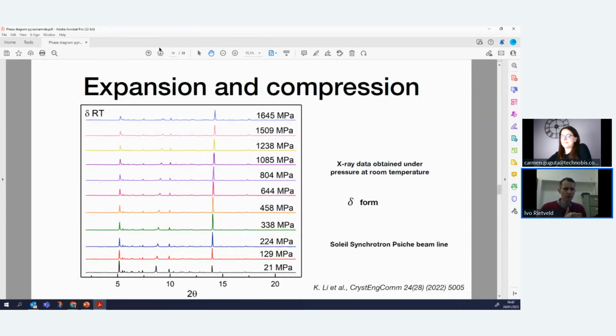Well, after that, obviously, this may not be of interest to anybody who is just interested in what the stability behavior is and roughly what my phase diagram looks like. But while we are academics, we like to go a bit deeper, a little bit further. So we also measured the specific volume of all the different forms, as a function of the temperature and as a function of the pressure. Here, this is just an example of the delta form, to show the expansion and decompression, or in this case, the compression under pressure of the delta form.